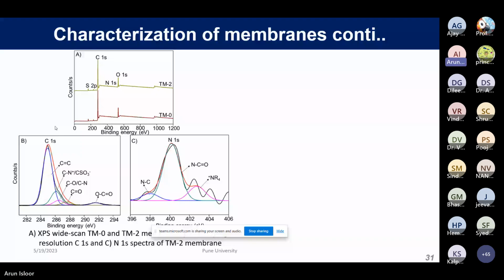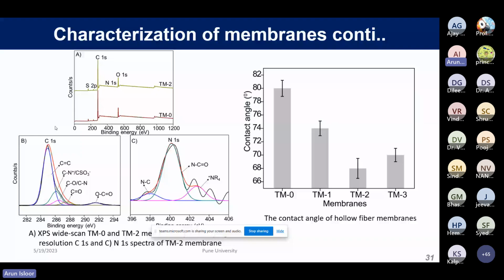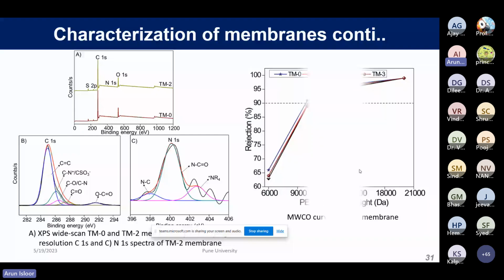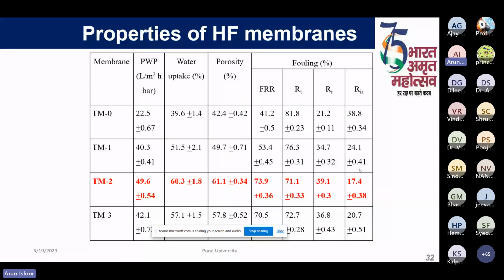Then these were incorporated in the polymer matrix, and flat sheet and hollow fiber membranes were fabricated. And you can see here TM0 to TM3, where the higher the contact angle, the lesser the hydrophilicity. So the lower the contact angle, that means TM2, the hydrophilic nature is more. So TM2 is found to be more hydrophilic in nature. And these are the other properties, that is the porosity and the water uptake. Again, the higher the water uptake, the better the hydrophilic nature.